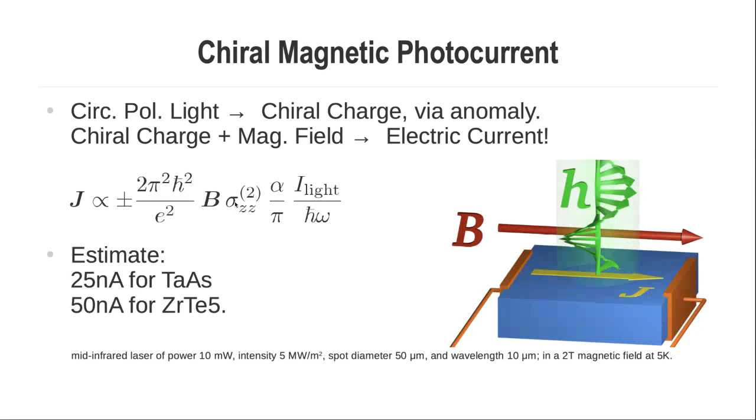The current itself doesn't depend on the resistance, but the way you measure it is by putting an external probe, which will have some resistance, and these are semimetals. So there will be an internal circulation of current. We have accounted for all those things in the estimate we have given. The internal circulation depends on the resistance of the material. The number of cones and the chirality flipping time scale have also been taken into account. Sorry, I made it look like it doesn't depend on anything.